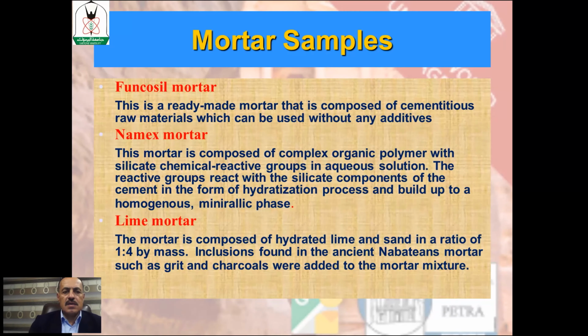the Nabateans. So Funcosil mortar is a ready-made mortar that's composed of cementitious raw materials which can be used without any additives. Namex mortar, again, is a mortar composed of complex organic polymers with silicate chemical reactive groups in aqueous solutions. The lime mortar is hydrated lime and sand in a ratio of 1:4 by mass, based on our analysis.